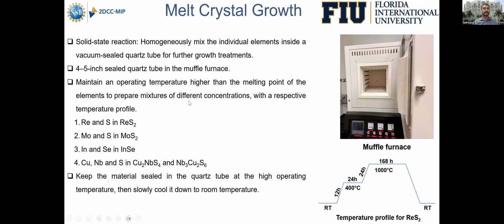For example, I have used different concentrations of rhenium and sulfur for rhenium disulfide, molybdenum and sulfur for molybdenum disulfide, indium and selenium for indium selenide, and copper niobium sulfur for copper niobium sulfide and niobium copper hexasulfide. I have presented one temperature profile for ReS2. We heated up the ReS2 from room temperature to 1000 degrees C and maintained it there for 7 days so that Re and sulfur homogeneously mix inside the quartz tube. After that, we slowly cool it down to room temperature and go with the other growth treatments.